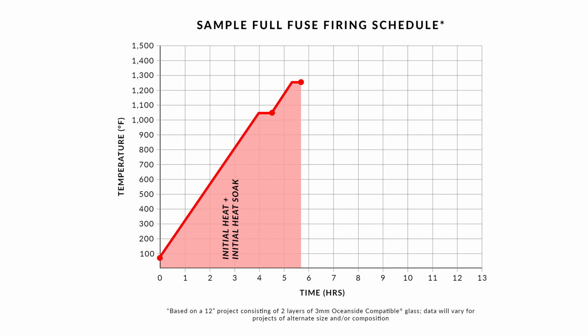For a 12-inch project made with 2 layers of Oceanside compatible 3mm glass, the initial heat and initial heat soak phase would consist of 2 segments. One that increases the temperature at a rate of 250 degrees Fahrenheit per hour, up to 1050 degrees, and holds it there for 30 minutes, followed by a second segment that increases the temperature at that same rate up to 1250 degrees and holds it there for 20 minutes.